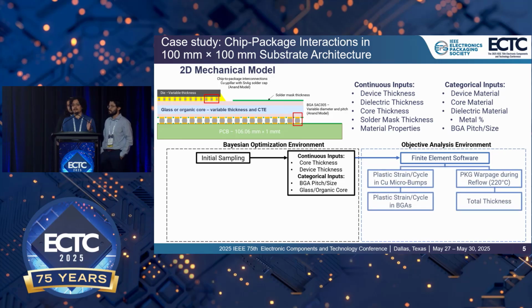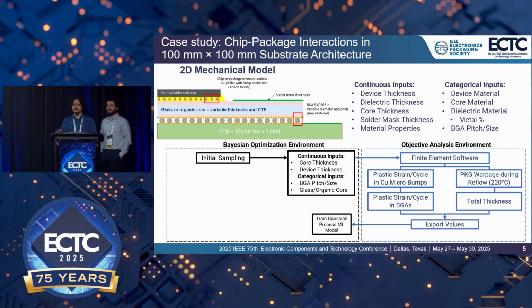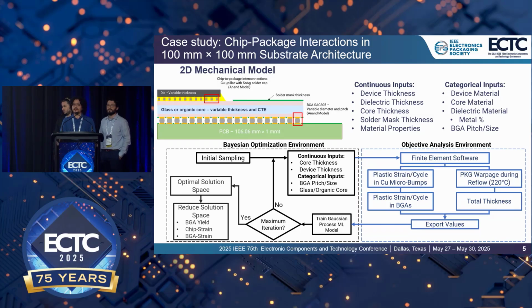Now, we feed inputs into the FEA, where we got the plastic strain per cycle for both solder joints at the chip and board level, the package warpage and reflow, and the overall package thickness. These outputs are fed back into the optimization loop, where we train the model, and lastly, we get the optimal solution that we can further reduce by filtering depending on BGA life and yield criteria.